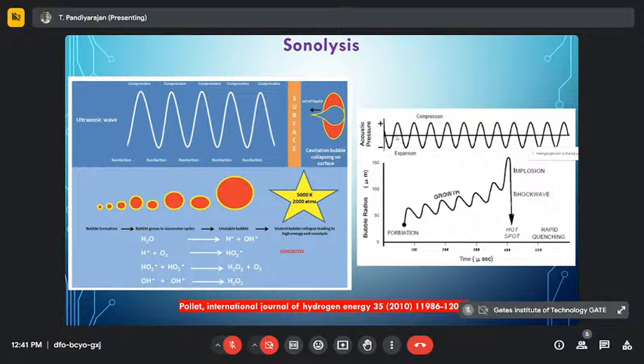Here you have acoustic pressure, that is compression and expansion, and if you send this wave into water, the bubble radius will try to increase, and once it reaches the critical size, it starts to explode. This very short explosion creates a kind of hot spot. If you check the temperature and the pressure, it is amazing: at micrometer scale, in the microsecond time scale, it produces 5,000 Kelvin temperature and 2,000 atmospheric pressure in that particular volume. This much high energy leads to breaking of the water molecule into radicals like hydroxyl radical, and ultimately you end up with production of OH radical and the formation of hydrogen peroxide.